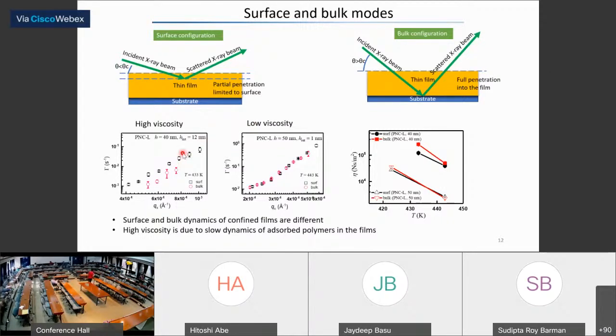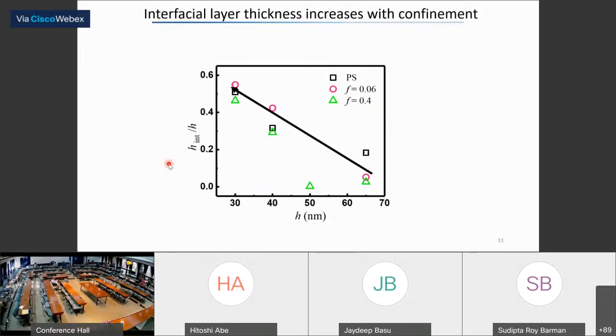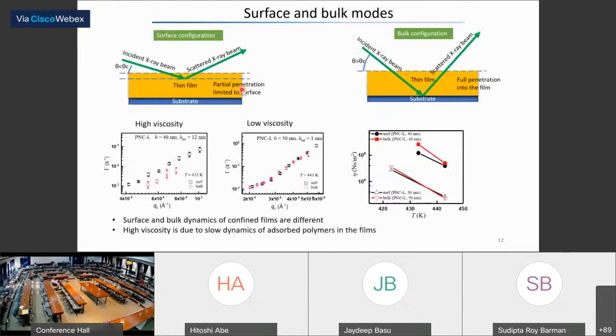So when we do that, if I highlight, you see that the rate here is actually faster. So this is measuring the surface dynamics. This is measuring the bulk dynamics for the same film at the same temperature. And you see that in this case, the interfacial thickness as we measured is larger. If you look at this case where that thickness is negligible or very small, then you don't see the surface bulk effect. So it's very clear that what I was showing here is really affected by the presence of this layer.